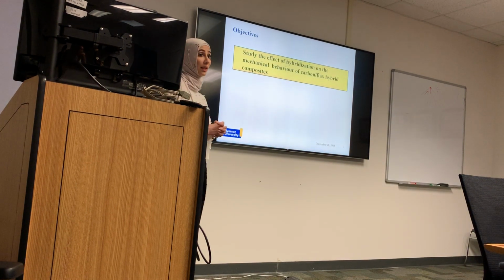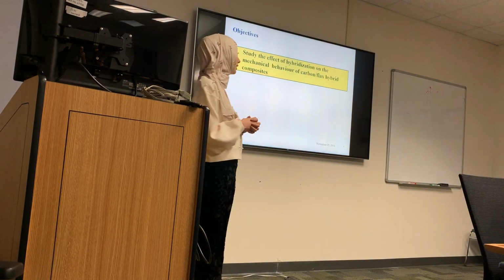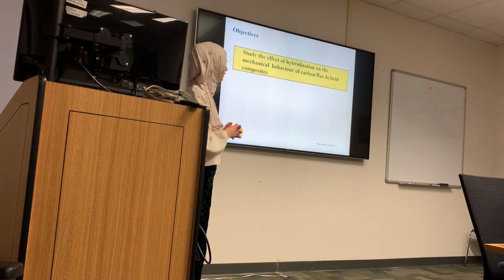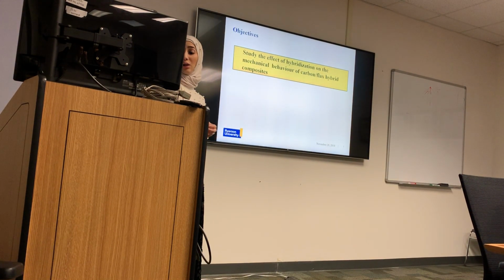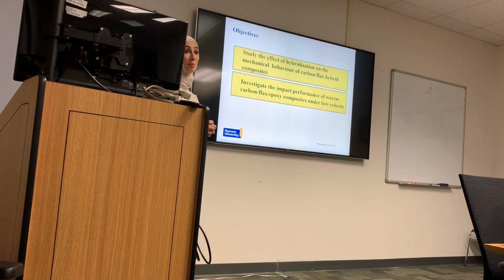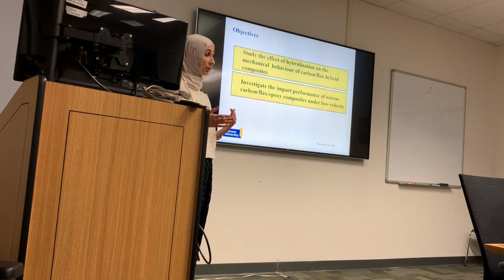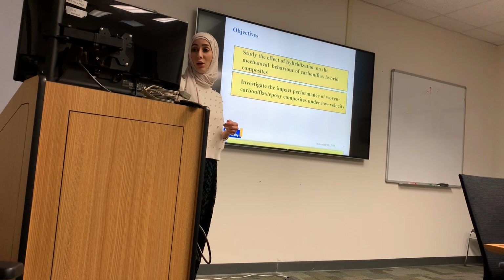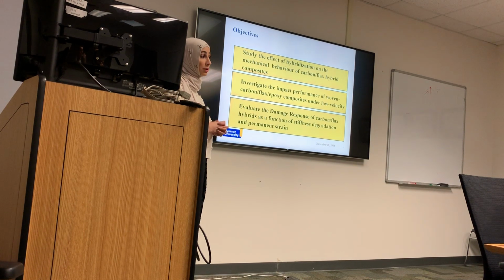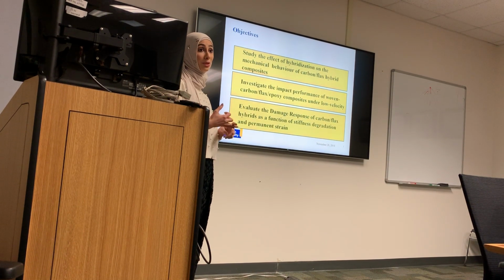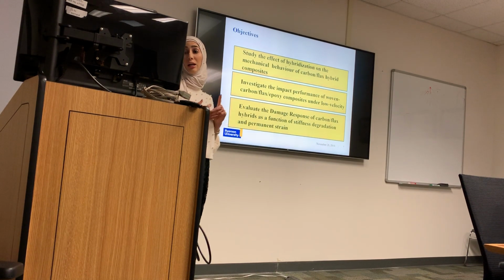Therefore, my objective is to comprehensively characterize the mechanical properties of the hybrid composites, and also their water absorption behavior. I also investigate the impact performance of the hybrid composite at low velocity, or low energy, between 5 to 40 joules. I also study the damage response of the hybrid composite as a function of stiffness degradation, permanent strain, and crack density.